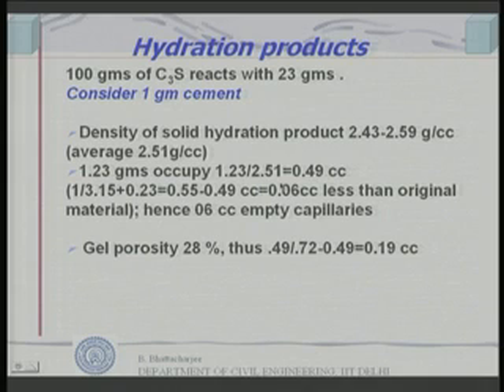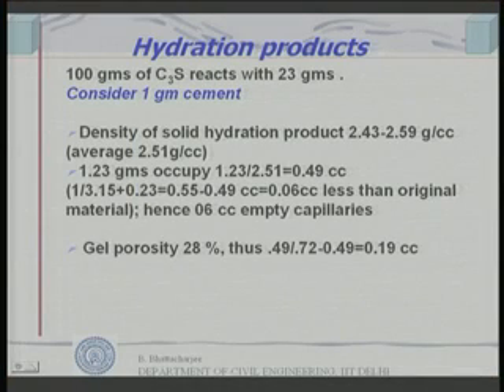But this 0.49 cc has an inherent gel porosity of 28%. The characteristic porosity of the gel is 28%. This has been determined from analytical chemical experiments. By various kinds of adsorption techniques and other analytical tests, people have found out that gel has a characteristic porosity of 28%. So whenever this 0.49 cc is there, it will always have 28% porosity involved in it, and by that calculation